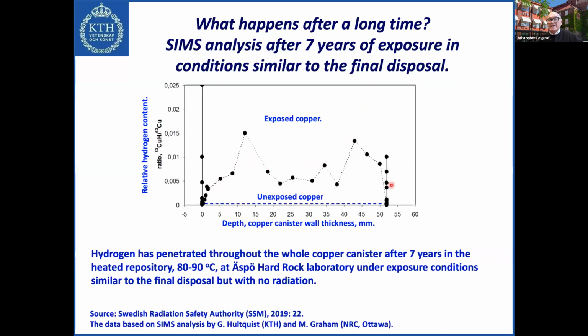These results, of course, at that time, they were published earlier, could not be understood really, but in view of the new results that we see here, where we really can see the detailed microstructural changes that occur and the introduction of these elements into the material, this now comes into another view, another perspective. So after 7 years, the results really show that all of the hydrogen has penetrated through it. Sulfur and oxygen were not measured in these conditions.